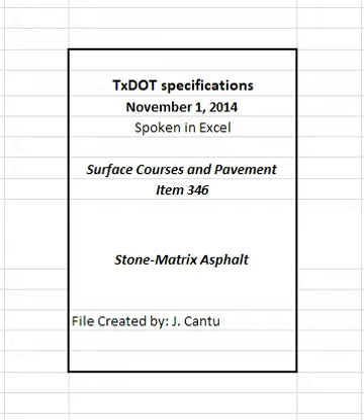If the department's or department-approved laboratory's sample from the trial batch fails the Hamburg wheel test, the engineer will suspend production until further Hamburg wheel tests meet the specified values. The engineer may require up to the entire sublot of any mixture failing the Hamburg wheel test be removed and replaced at the contractor's expense.